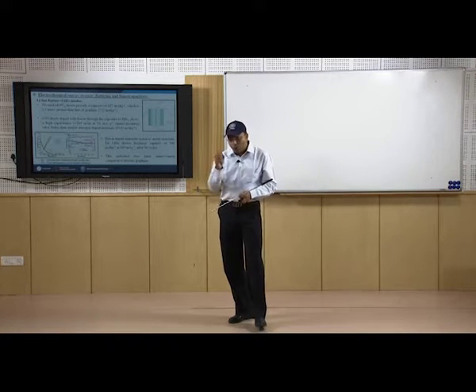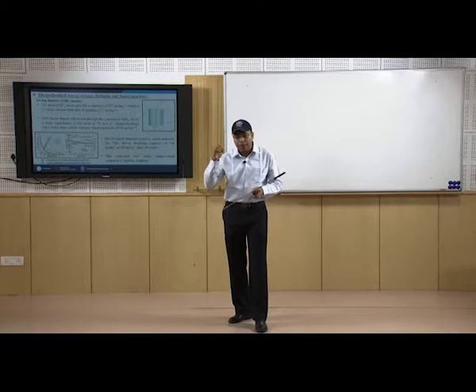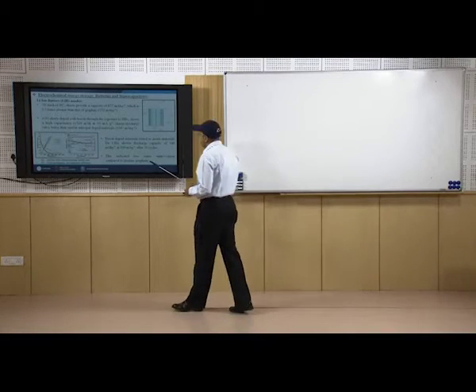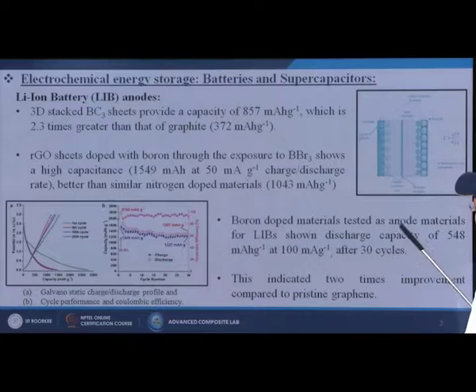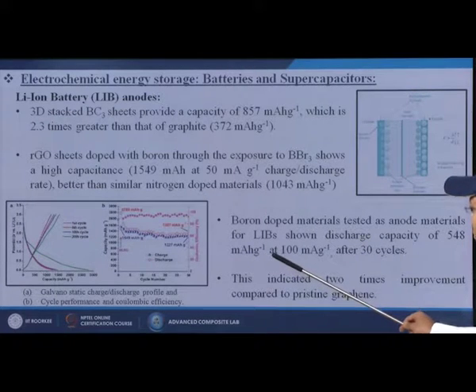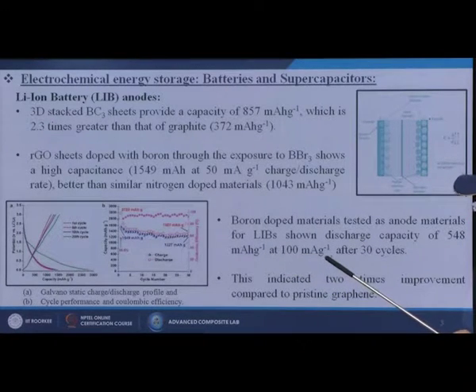So in that particular case, what we are trying to say is that when we modify these materials from the surface itself, or atomically, or when we use some kind of dopant or impurities inside it, the material's electrochemical properties are totally changing. And not only that, here also boron doped materials tested as anode materials for lithium ion batteries have shown a discharge capacity of 548 milliampere hour per gram at 100 milliampere per gram after 30 cycles. This indicated 2 times improvement compared to the pristine graphene.